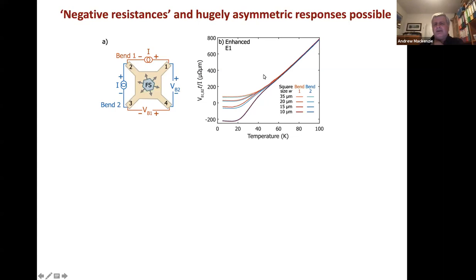Then as you go down in temperatures and enter the ballistic regime, you get into a position where, imagine you're passing current here, then you have many states all with the Fermi velocity in the same direction. So you have a very high probability ballistically of transmitting those electrons, pumping them straight through the device to build up charge in the opposite contact. And as they build up that charge, that distorts the voltage that you would be measuring there away from ohmic, and it can even lead to the voltage going pronouncedly negative. Now that was seen in the 90s in the semiconductor devices, and it doesn't really matter, apart from slight deviations in device perfection, whether you apply the current in that orientation or that one.